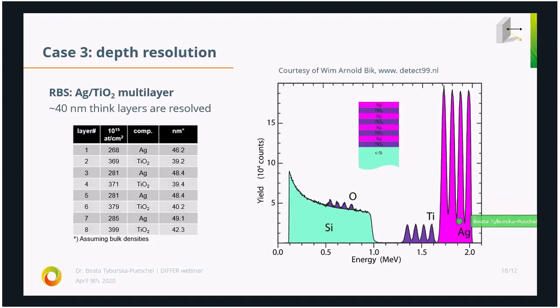You can see here the pink signal is the silver signal, and you can see four peaks which correspond to each of those layers, where on the right you have the most top layer, and here is the most bottom layer. Then you can see four peaks for titanium. Again, here you have the most top layer, here is the most bottom. And then we can even see oxygen from the titanium oxide on top of the silicon substrate signal. The thickness of those layers was usually between 40 to 50 nanometers, and we can easily distinguish them. And quite frankly, if they had been even thinner, we would have been able to resolve them as well.